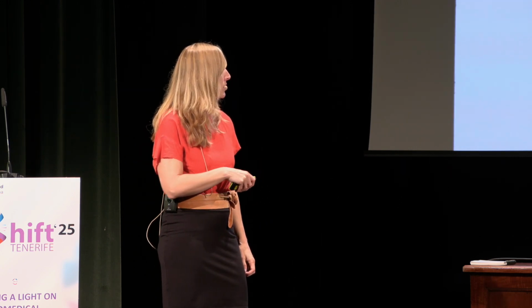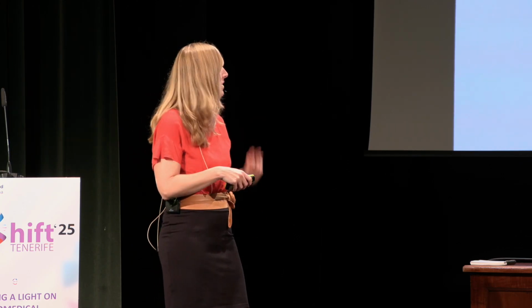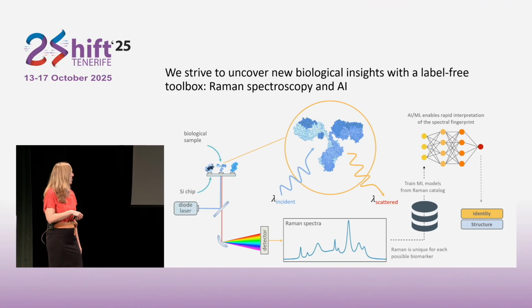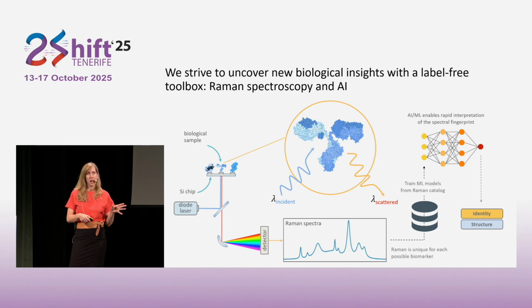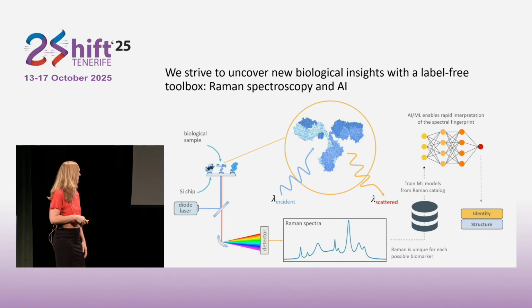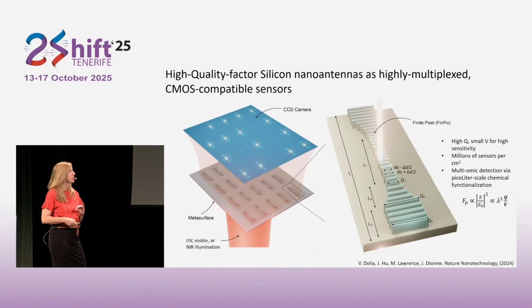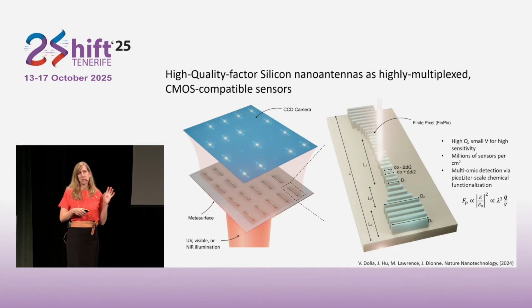And then what we're able to do is not only boost Raman spectroscopy to, in some cases, the single molecule level, and certainly the single cell level, but then also gain interpretability of that Raman spectra by looking at different vibrational peaks and collections of peaks to provide interpretability as to what sort of molecular vibrations they correspond to. So I'll spend a few minutes just discussing the particular sort of chips that we're using to enhance Raman spectroscopy. I would say all of them tend to be close cousins of one of the first high-quality factor metasurfaces that we made in our lab.